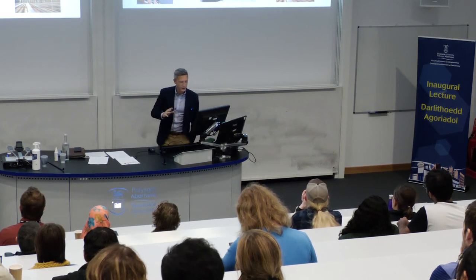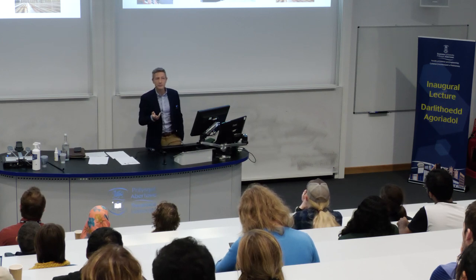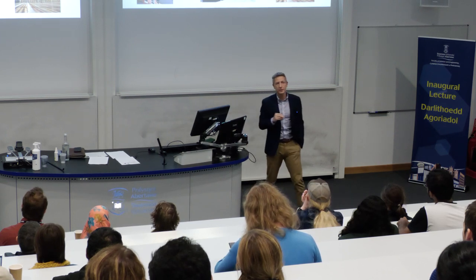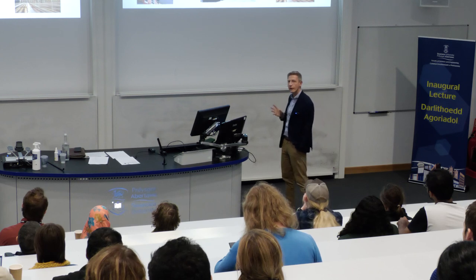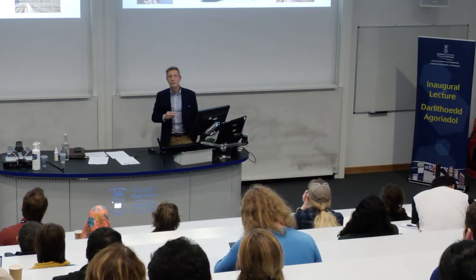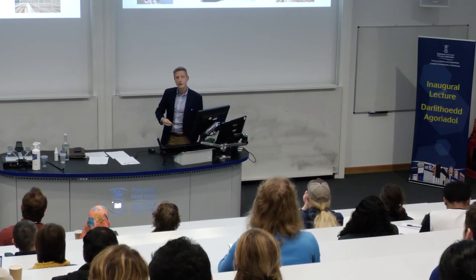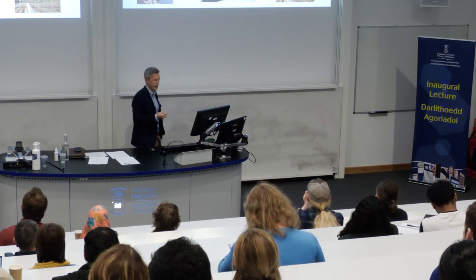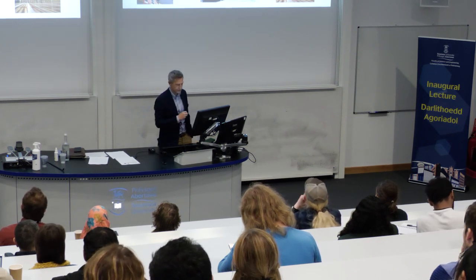These are around 18 to 20% efficiency. They still require vacuum deposition, which is very expensive. We can put multi-layers of these semiconductors together and they're very efficient, so up to 45% efficiency, pushing 50% in cases. But they rely on elements that we simply do not have enough of on Earth to deploy the amount of capacity we need. So they are mostly used for space applications and small-scale applications.